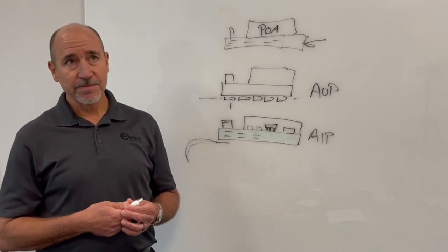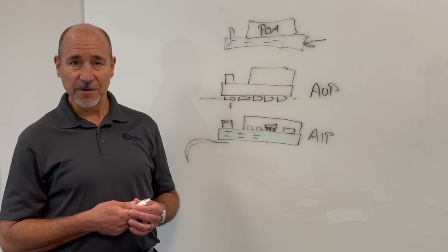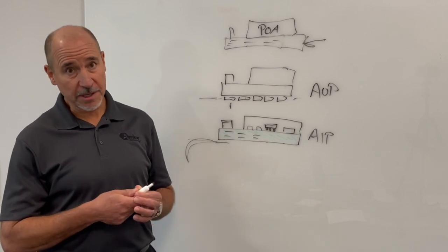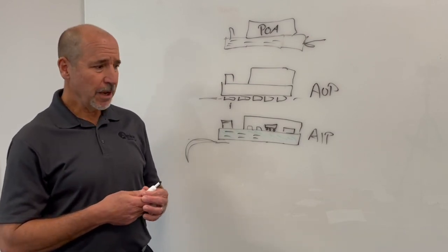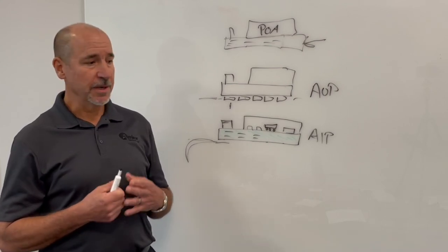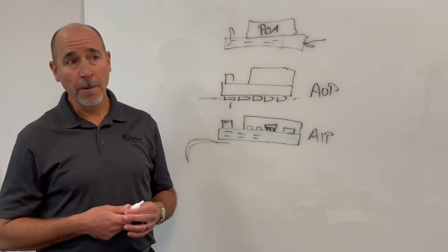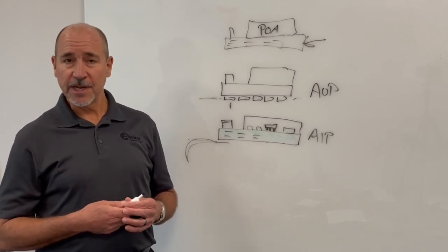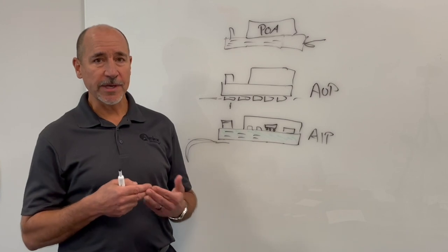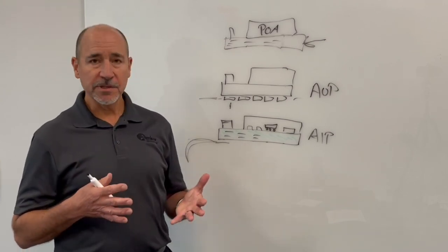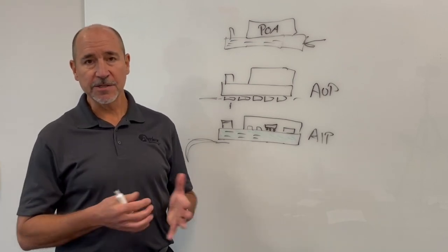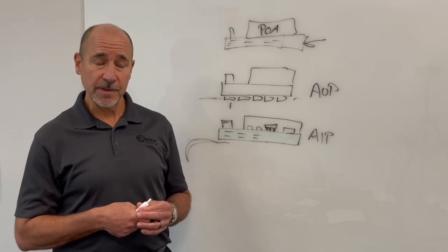The challenges with glass is it's difficult to process with regard to via formation. Various techniques can be used, and those are being optimized, and that supply chain is currently not well-established. It is becoming so. Also, glass is very conducive to panel-level packaging, especially for core substrates. So panel-level packaging is an exciting area that glass could play a large role. And the challenges continue, though, since this is a new technology for packaging, is cost in the supply chain, and bridging those gaps where we need to have a very high capacity, ultimately, and scale via formations, filling the vias, and then having good handling techniques so we don't have any damaging or any damage during the assembly process.